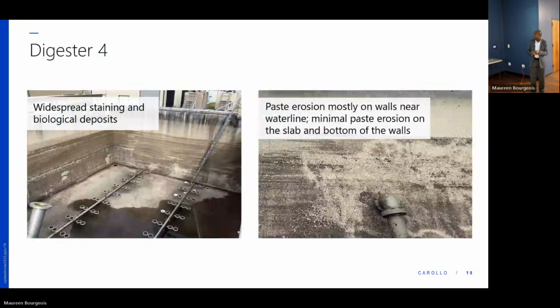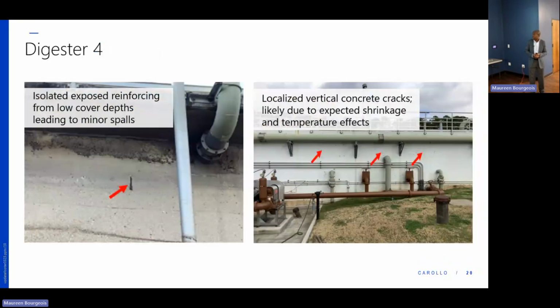At the bottom of the walls and to the slab, none of that was observed, which is typical for such structures. In one end of digester number 4, though, we talked about the concrete cover. So there you can see particularly a reinforcing being exposed. Likely the concrete has spalled off or broken off due to some corrosion, something happening there.